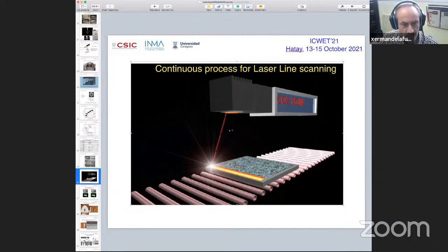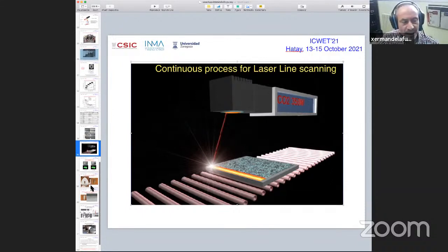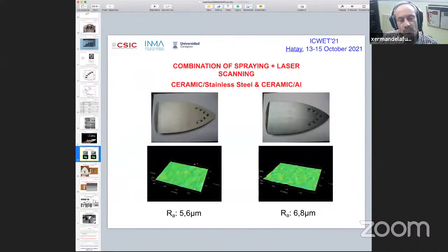I think this is a simulation, but it will show you how the laser line scanning process can be performed in large areas, so that we combine beam scanning, very fast, with line scanning by moving the sample at a constant rate, like it's done in many applications in industry. But this is not working, sorry. But we can work, for example, on these domestic applications where previously deposited thermal sprayed ceramics are then sealed and restructured, and the microstructure controlled by laser line scanning, as you see here, where the original surface roughness is also reduced.